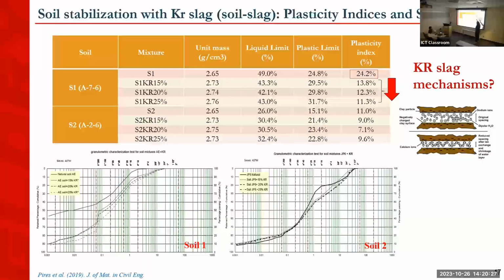But when we add slag, first thing that we noticed was the reduction of plasticity index. And this reduction was observed for the two types of soil. Soil 2 was more like a sandy soil. So we observed that for the clay soil, the reduction in plasticity index was higher than in the sand soil.